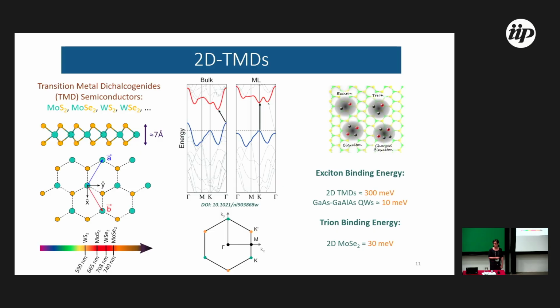In addition, it has a strong binding energy of excitons as compared to, for example, III-V semiconductor materials. The binding energy is 10 millielectron volts, while in 2D it is 300 millielectron volts, so at room temperature you have an exciton. It's very strong, and it's a very nice system to investigate, for example, excitons and trions, when you have 2 electrons and a hole bound with Coulomb interactions. So it's a very nice system to investigate exciton complexes.